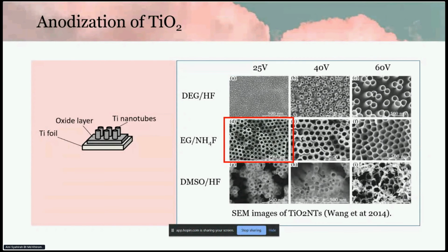The figure on the right shows the cross-section of nanotubes under SEM in different types of electrolytes, all containing fluoride ions and applied with different voltages. As you can see, results show that the nanotubes are formed effectively with distinct features in ethylene glycol electrolyte containing ammonium fluoride at 25 volts. It can also be observed that the nanotube holes and diameters are consistent compared to the other images, which show irregular shapes.